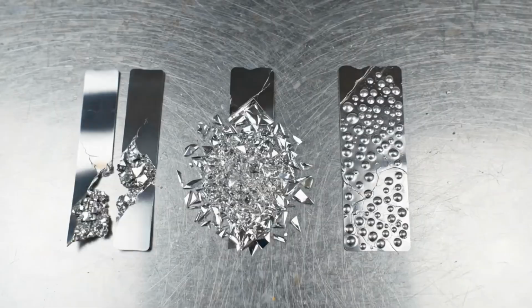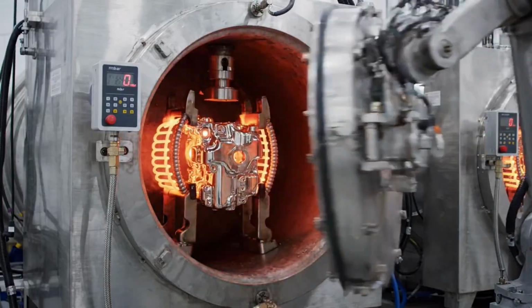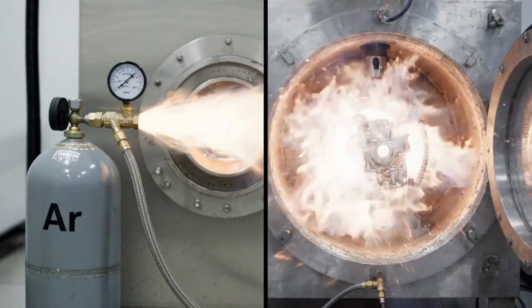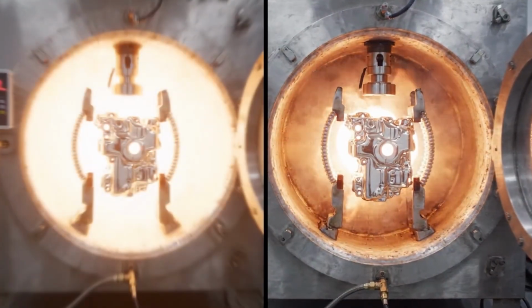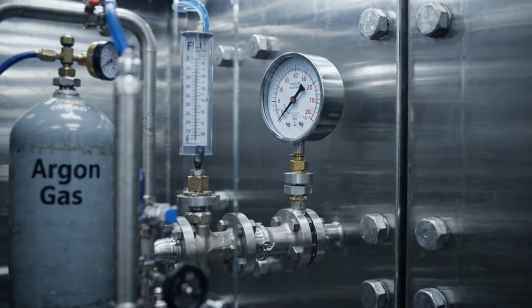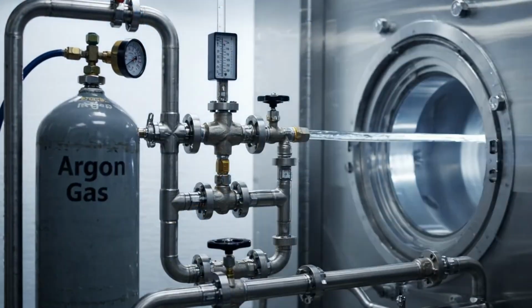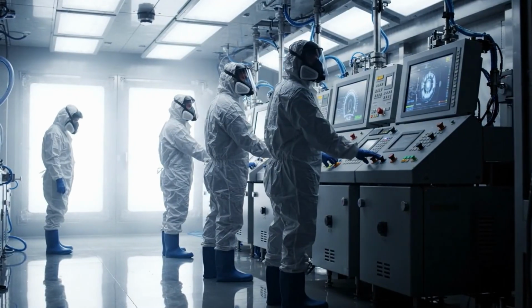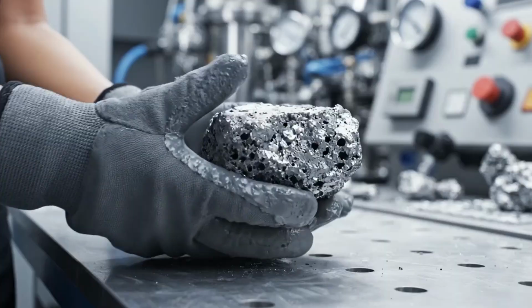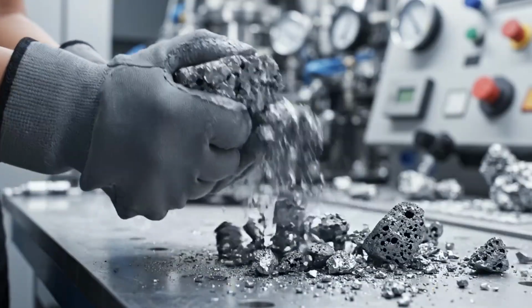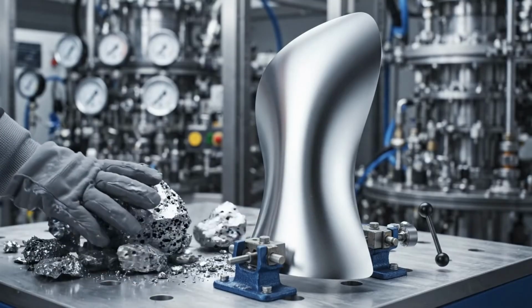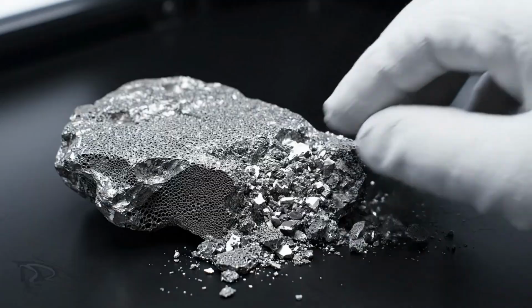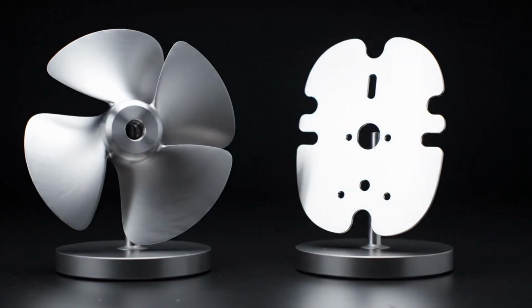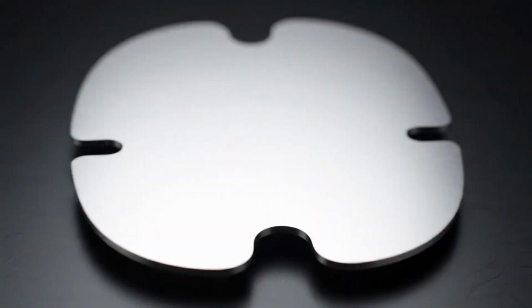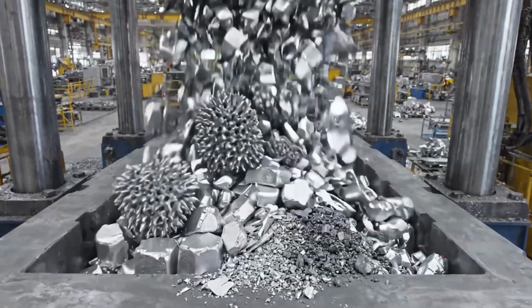Titanium sponge is already metallic titanium, but it's not yet suitable for manufacturing a turbine, a surgical plate, or an aircraft structure. It must be transformed into a homogeneous solid. To achieve this, it is pressed into electrodes or compacted together with selected titanium scrap and alloying elements. It is then melted in special furnaces. One of the most widely used methods is vacuum arc melting. In this system, a titanium electrode is melted inside an evacuated chamber without contact with air, and the molten metal falls into a cooled copper mold where it solidifies into an ingot.